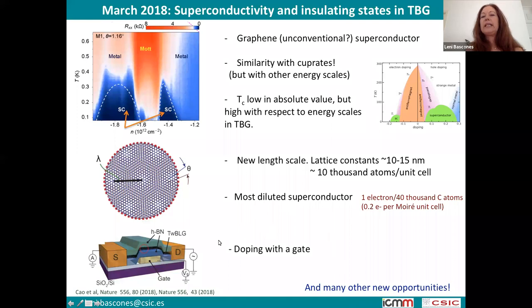But another thing is that they can be doped with a gate. Normally, if one is doping in a cuprate, you have to change the sample and so on, and you can dope very little, because doping atomically, you can only dope like 0.1 electrons per unit cell, 0.2 electrons, something like that. Here you can dope with several integers.